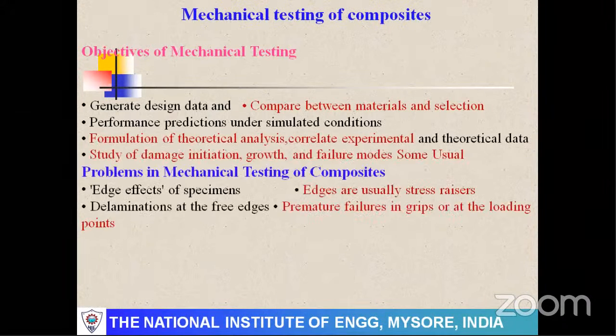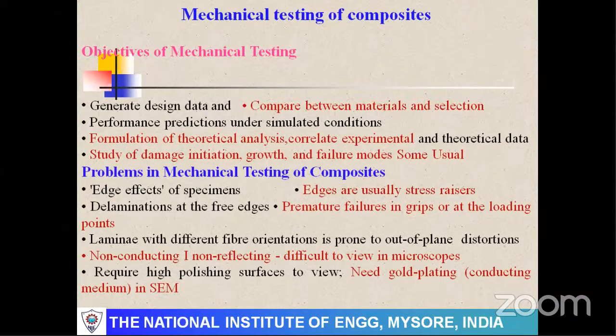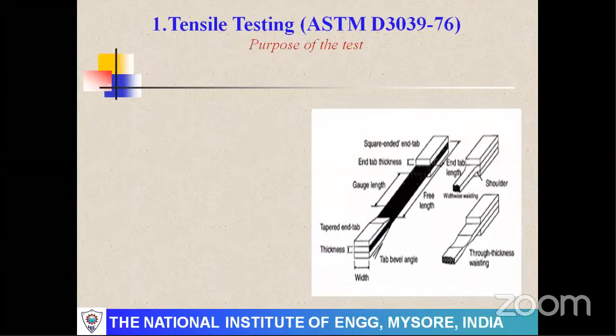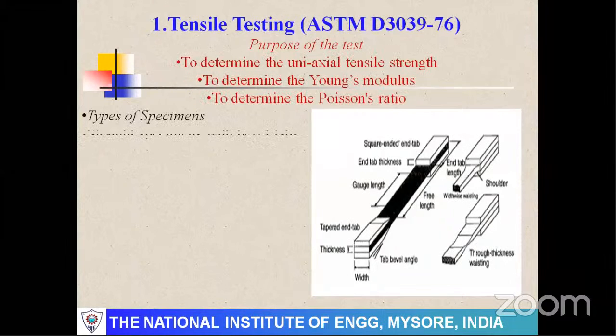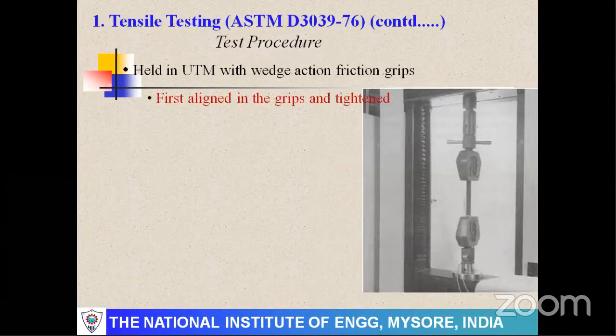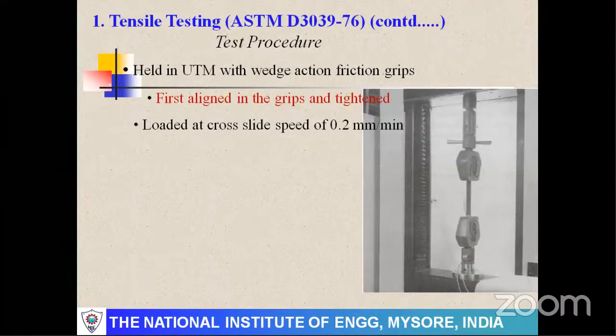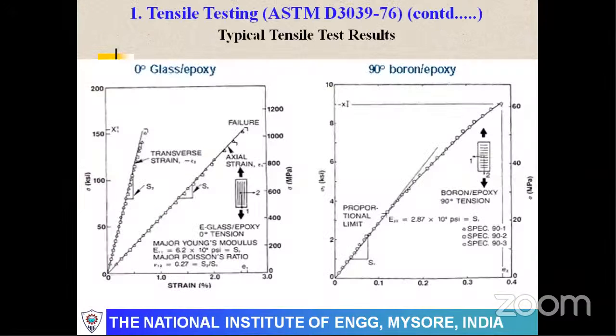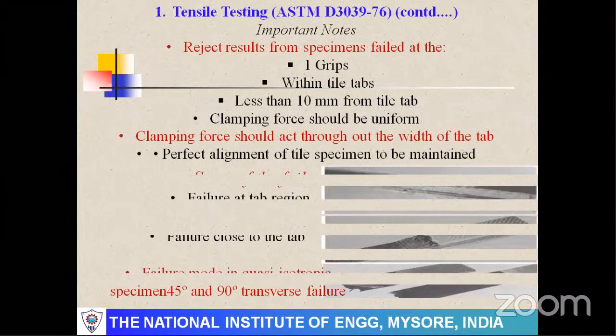Coming to mechanical properties, because of time I will not go through them. As per ASTM D638, this is the equipment you can use. Alignment of the sample should be unidirectional. Then see how those tests are conducted, so that you will come to know the stress versus strain, and how the failures, fractography, you can analyze.